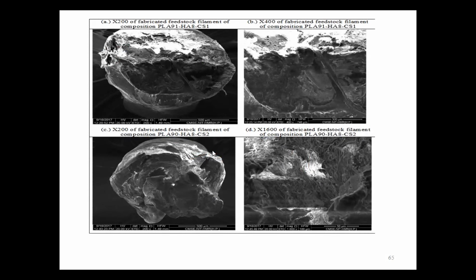And here is the one important thing that we learned from this: we tried to see the SEM images of this. And if you see, this is at 1600x, I am getting an open porous and fibrous structure. What does this mean? If I have the two parts of the bones, and in between there is a PLA as a spacer, and with the hydroxyapatite and chitosan, from one part of the bone, the osteoblast cells will start to grow and will move to the other part, and we will get an open porous and fibrous structure. So we result in the interbone type structure, right?